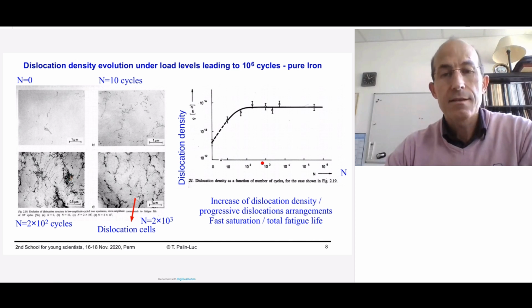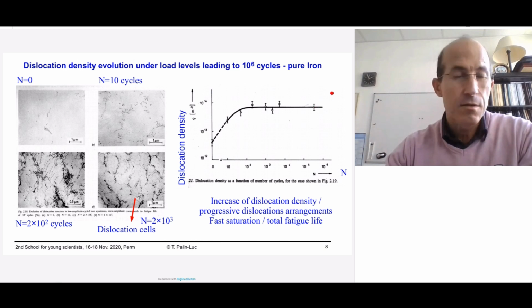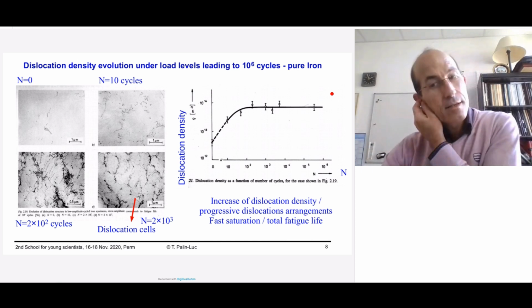You can see in this diagram, which plots the dislocation density versus the number of cycles on a logarithmic scale, there is an increase of the dislocation density during the beginning of the cyclic loading, up to approximately 100 cycles here, and then a saturation plateau. And if you continue the test up to fracture, there is an avalanche phenomenon which creates the crack initiation.